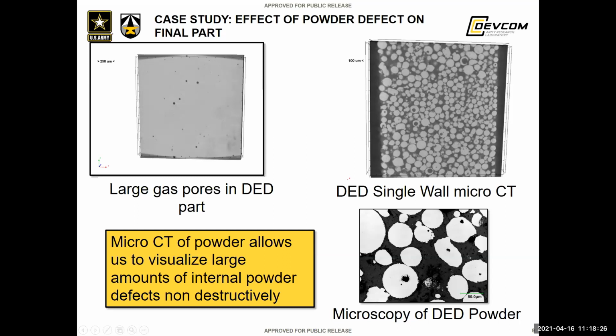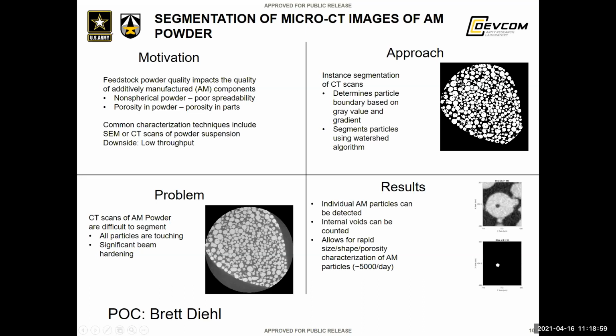With CT, we're actually able to see large amounts of the powder and go through the powder and see the volumetric, how much of the volume is defects. So with CT, we're able to visualize a larger amount of internal powder defects non-destructively, in a time faster than it would be to mount the same amount of powder and investigate it. But the issue, in terms of segmentation of micro CT images, at least with the software on hand, is that it's a little bit harder, as a person doing it, to segment the actual particles themselves.